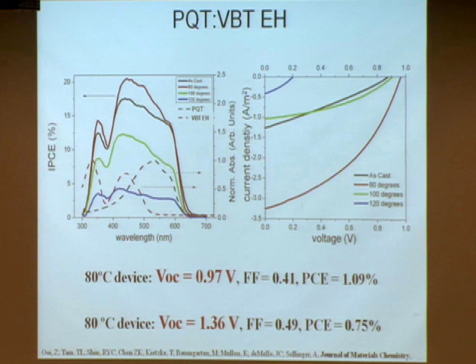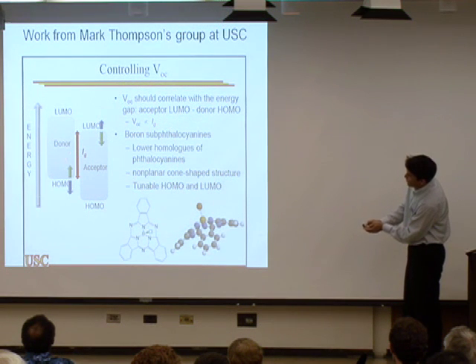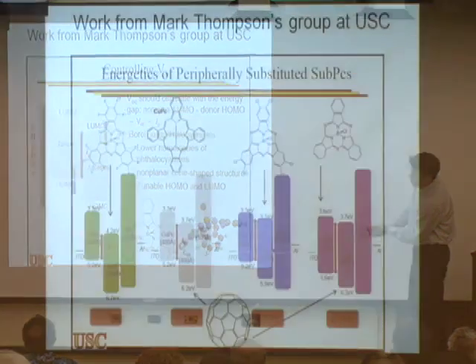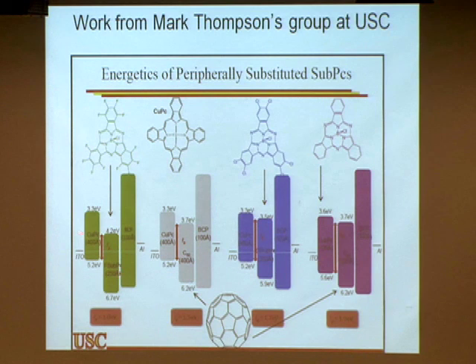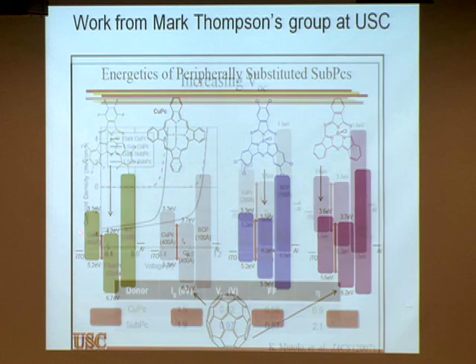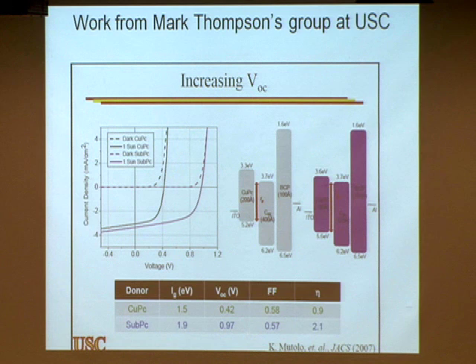So Mark Thompson also is interested in this area, looking at VOC. In this case, we have a donor and acceptor, and this IG is proportional to the VOC. So he is also working with different donors and acceptors and trying to move around this value. So here in this complicated slide, we have this CuPc, this copper phthalocyanine that Mike mentioned earlier in the talk. And then by introducing different materials into the acceptor side, we can change this IG, which in turn changes the open circuit voltage. In the next slide, you can see that by changing the materials combination, he improved the open circuit voltage from 0.4 to almost 1 volt, and that in turn improved the power efficiency of the device. So this is another way to work with certain parts of the energy levels to increase the performance of your device.